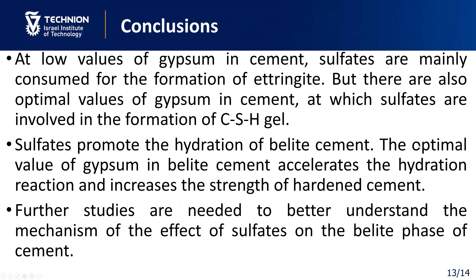During this research, we arrived at these conclusions. At low values of gypsum in cement, sulfates are mainly consumed for ettringite formation, but there are also optimal values of gypsum in cement at which sulfates are involved in the formation of CSH. Sulfates promote hydration of belite cement. The optimal value of gypsum in belite cement accelerates the hydration reaction and increases the strength of hardened cement. Further studies are needed to better understand the mechanism of the effect of sulfates on the belite phase of cement.